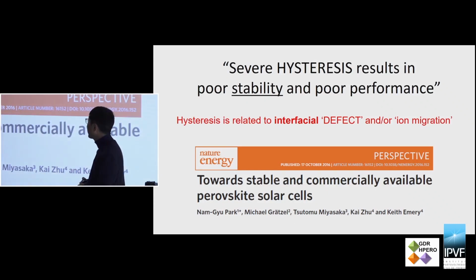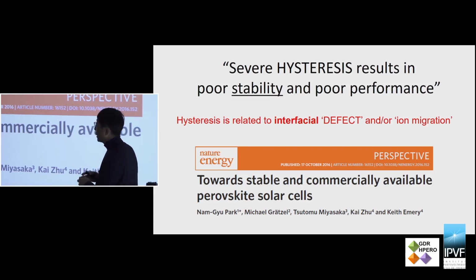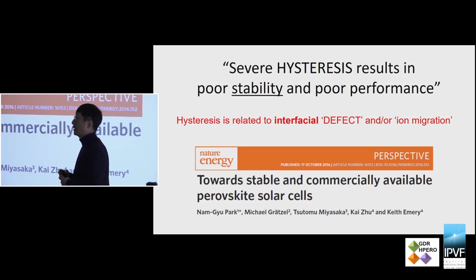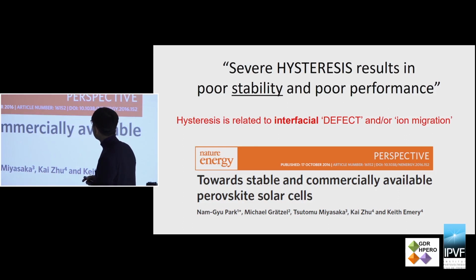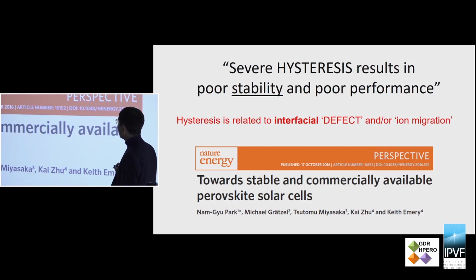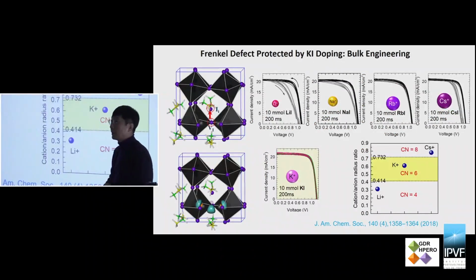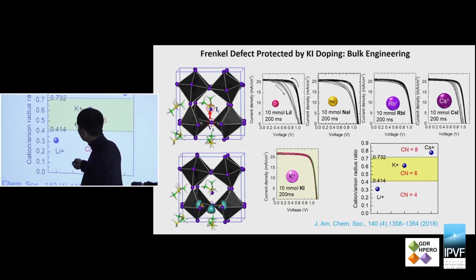So in terms of stability, stability is also related to the hysteresis of the perovskite solar cell. If you see very severe hysteresis in the solar cell that you made, that means you have large defects in the perovskite material or the solar cell. So defect engineering is also very important to reduce the hysteresis and guarantee long-term stability. For instance, this is the reverse scan and the forward scan. If the two scanned IV curves are not well matched, then you say this is hysteresis.